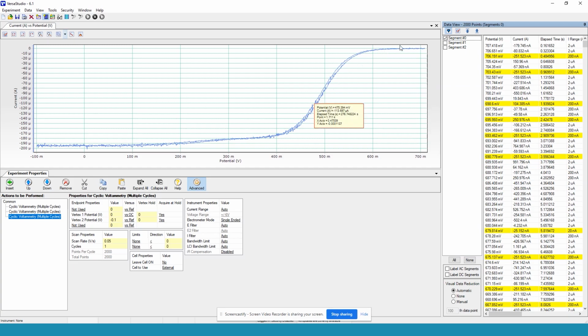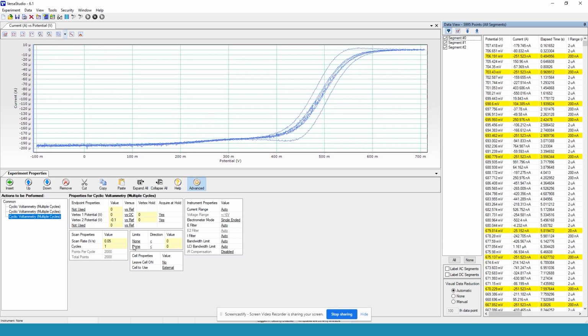We also see that on the return scan, we no longer have the formation of an oxidation peak. This is because the species that we have reduced in this area will be washed away, so they cannot be oxidized in this area. Now, the point of this experiment was that we would compare the effect of the scan rates of the different experiments. And we can quite clearly see that the faster scan rates will lead to a more deviation compared to the slower scan rates. So the point here is we want to see how fast can we scan without this deviation becoming too big of an issue. That's why we want you to also plot the current we see at, for example, this point to the current we see at this point for all different scan rates.